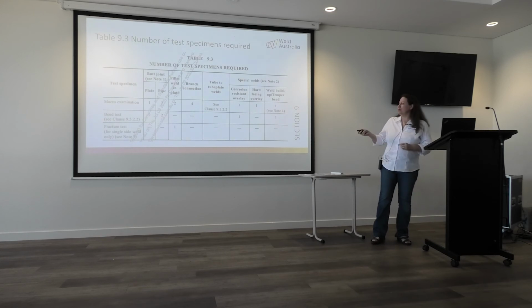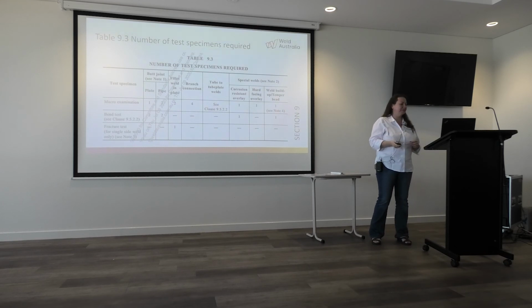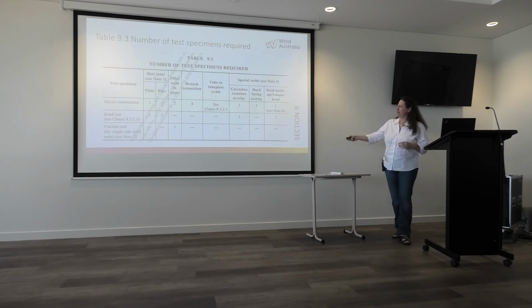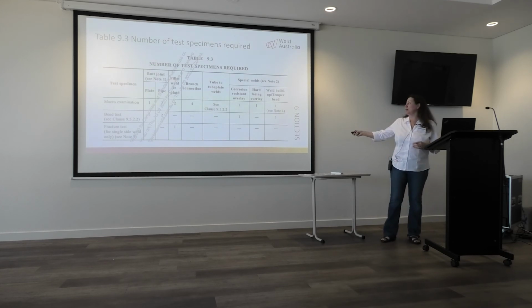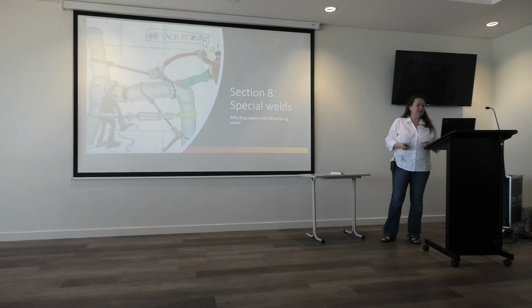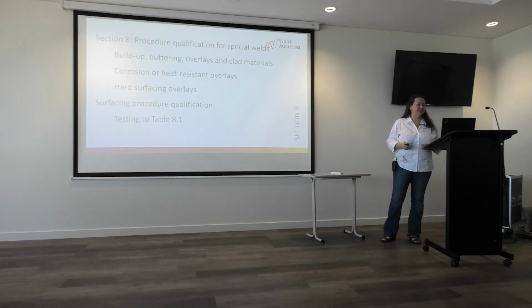So that was the big requirement, that fracture toughness, bend testing in the notes is actually added for the processes that are susceptible to lack of fusion. And then requirements were put in for your special welds, which I'm going to skip now, but your welders need to be qualified to actually weld these special welds. So the special welds are the repair section, and this section is the biggest update. So defining what's a buttering, building up, overlays and cladding.